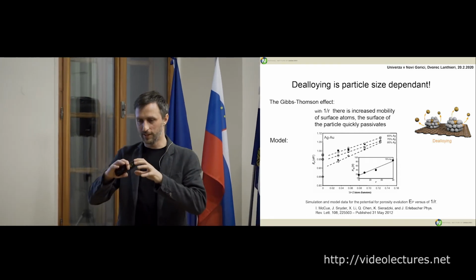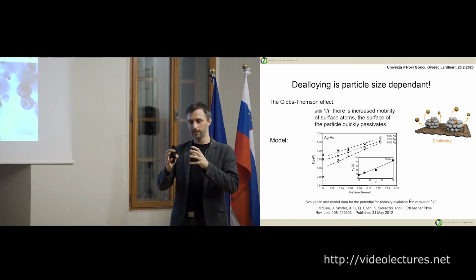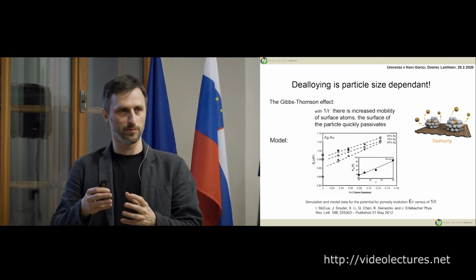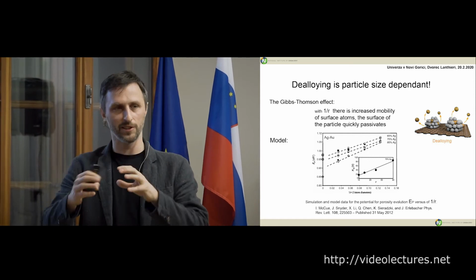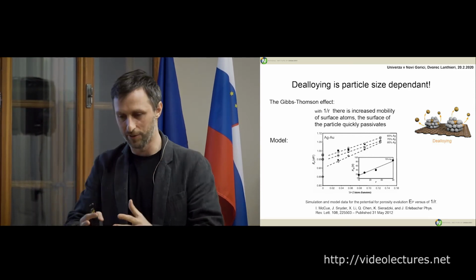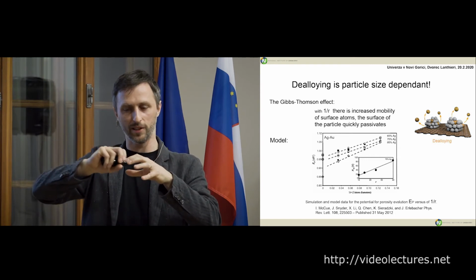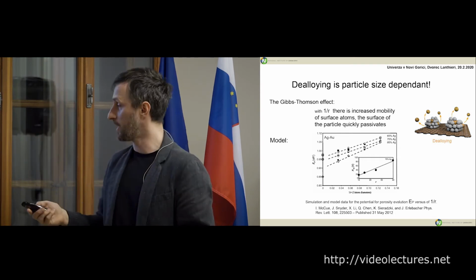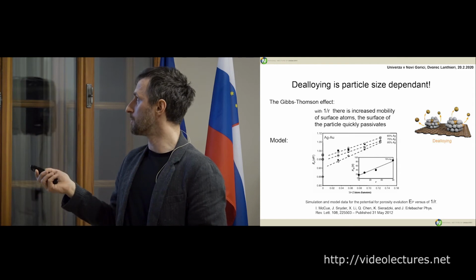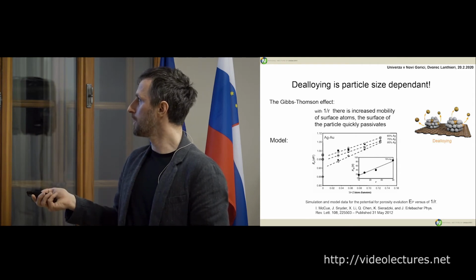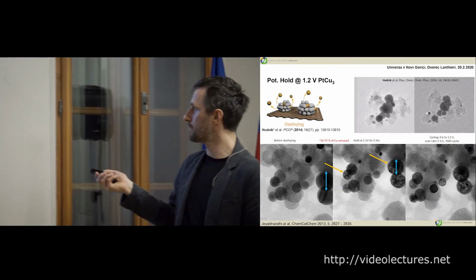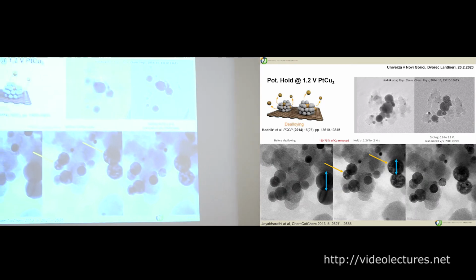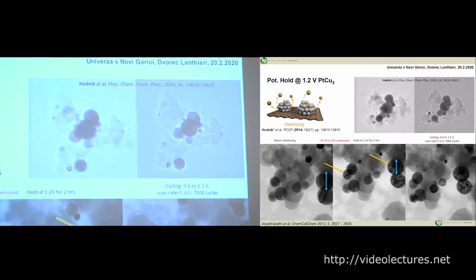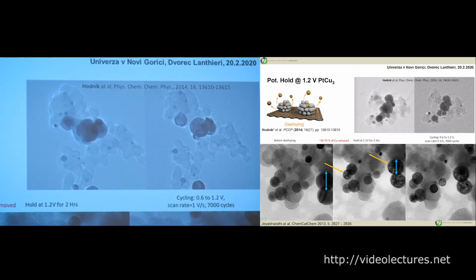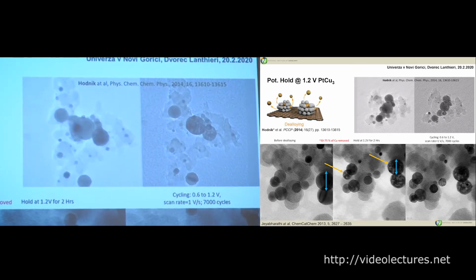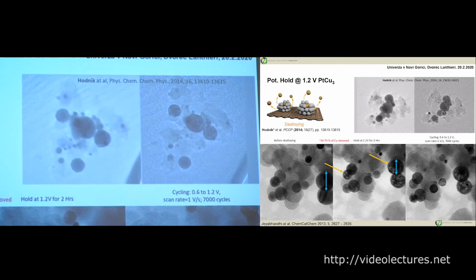And this means that the smaller the particle, the less chance that it will become porous, because the platinum is faster on the surface and it's like healing the surface. If it's bigger, it's slower, so the copper has time to escape. And this was nicely shown here. Of course, we also did tomography on the same location, but you see the bigger particles make pores, and the smaller ones stay the same. And the porous ones also shrink because you're losing 50 to 75% of copper, depending on the particle size.